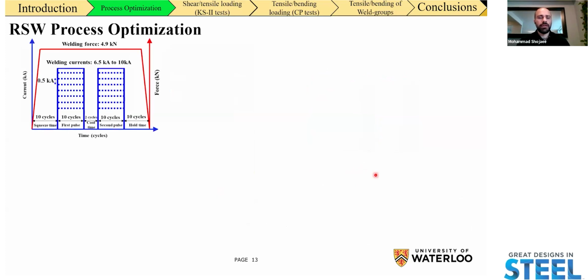In terms of the RSW process, we're using a double pulse welding schedule that was suggested by the American Welding Society standard. That's the most commonly adopted standard in North America for spot welding. Now, we actually changed the welding current from a really low amount, around 6.5 kiloamp, up to 10 kiloamp to attain different nugget sizes. Our squeeze time was 10 cycles. The length of the pulse is also 10 cycles, with 2 cycles in between the two pulses